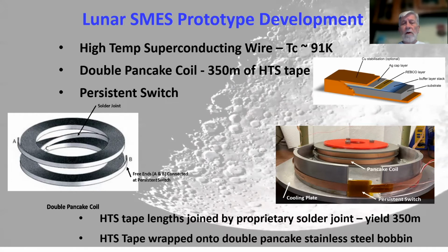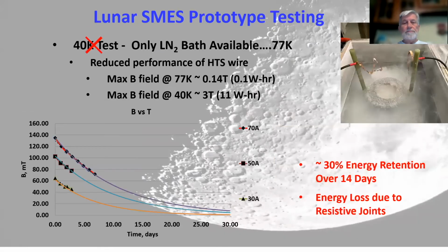We had a double pancake coil design, about 350 meters of HTS tape, and a persistent switch to allow switching of the coil into a persistent mode. The coil was mounted on a cooling plate, and that cooling plate would be mounted on a cryocooler to be able to get down to 40 degrees Kelvin. We used 350 meters of tape made out of short segments, so we had a number of solder joints that were resistive joints, and as a result, we had energy loss due to that, as I'll talk about later. And we had the HTS tape wrapped on a double pancake stainless steel bobbin, a significant additional weight, but we changed that also.